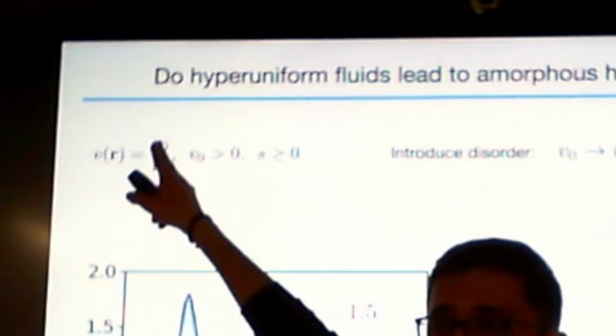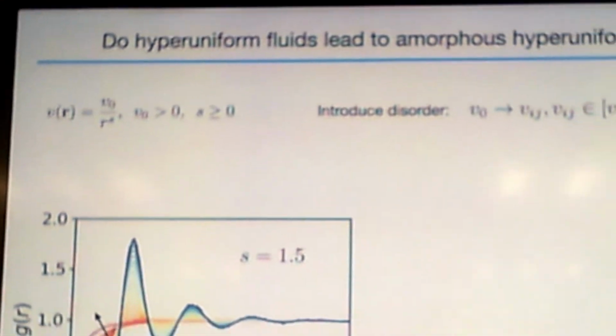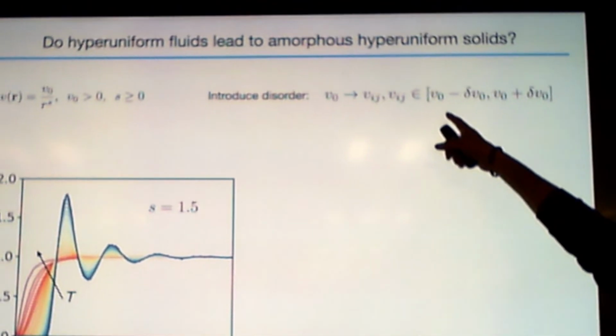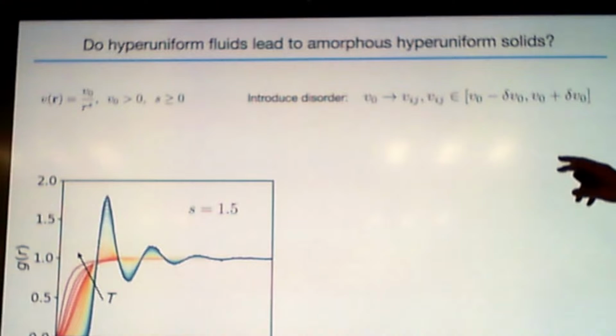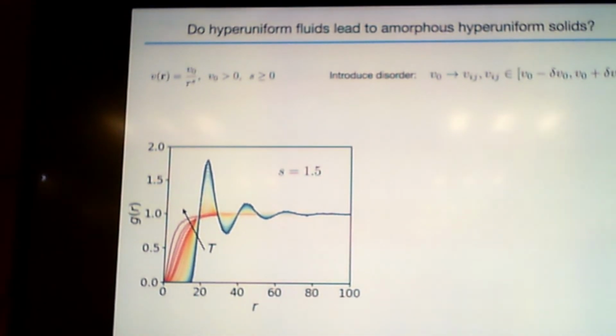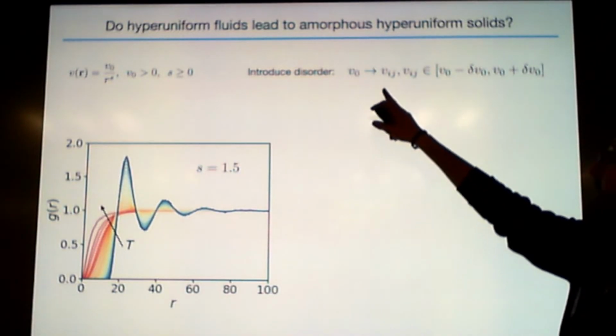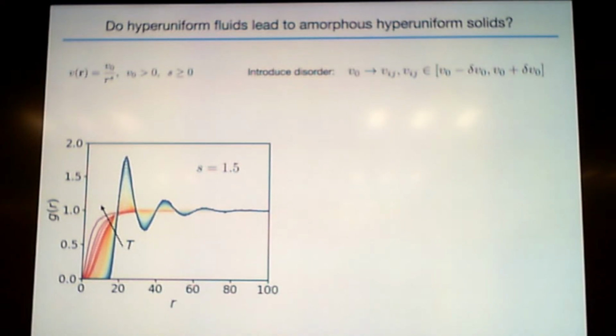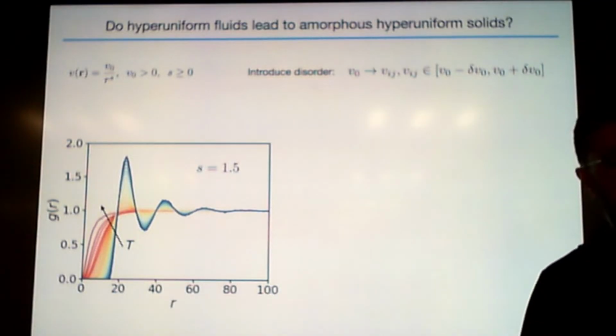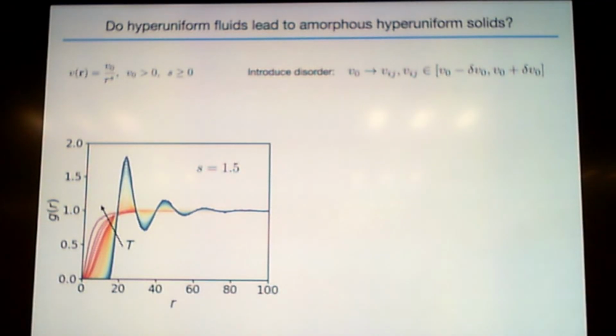Now what we are going to do is introduce disorder in the V0, in the interaction amplitude. So we are basically sampling the interaction amplitude from a uniform distribution around the V0. And we are now assigning pairwise interaction amplitudes. So each particle pair has a different interaction amplitude now. The width of this distribution is given by delta. If delta is too small, if the interaction amplitudes differ only slightly, as I will show, you still end up in a crystal. Only if these interaction amplitudes differ enough, you end up in a non-crystalline amorphous state.